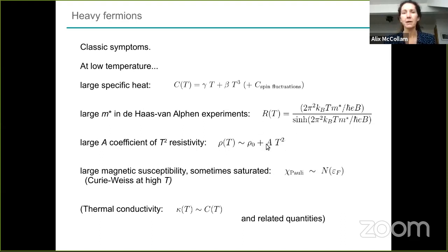not always Fermi liquids, or do not always form Fermi liquids, but when they do, the A coefficient tends to be large. And then in the magnetic susceptibility, you have at high temperature typically a Curie-Weiss susceptibility, and then at low temperature, this tends to saturate. Again, if it's a good Fermi liquid, you have a Pauli-like susceptibility. If it's not, you sometimes see some other behavior. So the behavior of the specific heat and of the susceptibility are not unique at low temperatures, but they are typically strongly renormalized, so related to a strongly renormalized density of states. Things like thermal conductivity and many other experimental quantities are related typically to some of these quantities, so they show similar characteristics related to an enhanced density of states.